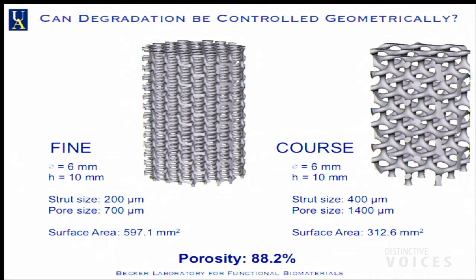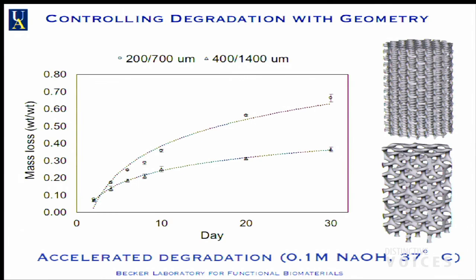So here are two different test structures. This is what's called a fine structure. This is a coarse structure. 6 millimeters across, 10 millimeters tall in both cases. This one has a 200 micron strut, this one has a 400 micron strut. 700 micron pore, 1400 micron pore. Basically 88% air, so 12% solid. This one has half the surface area of the other. And so if this degrades due to water absorption and hydrolysis coupled with enzymatic action, then higher surface area should degrade faster. In this particular experiment, we've got the same material, the 1800 Dalton material. This is an accelerated test, kind of like cheating. Over 30 days, this is mass fraction of material, and you can see, it's a little small here, these are triangles, these are the circles, that with higher surface area, you degrade much faster.